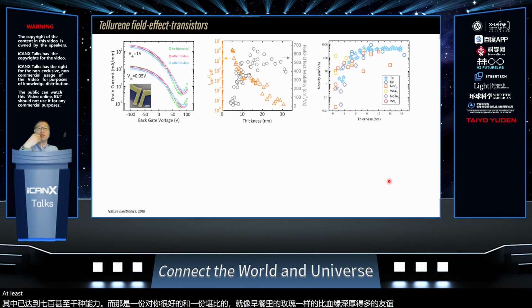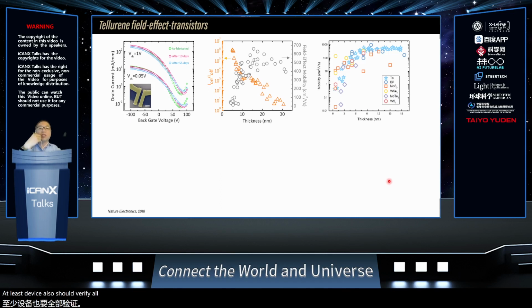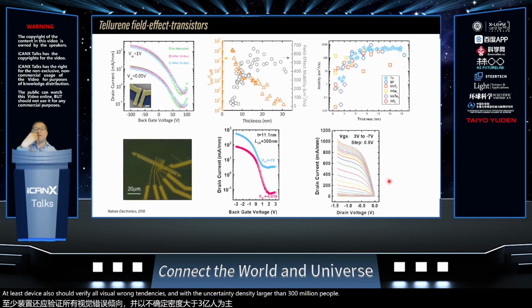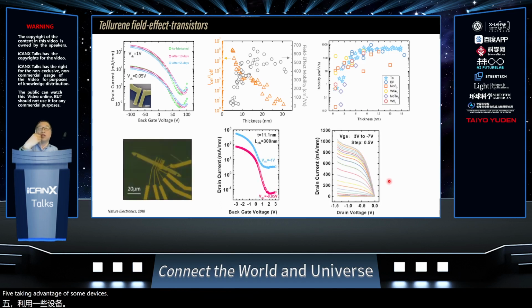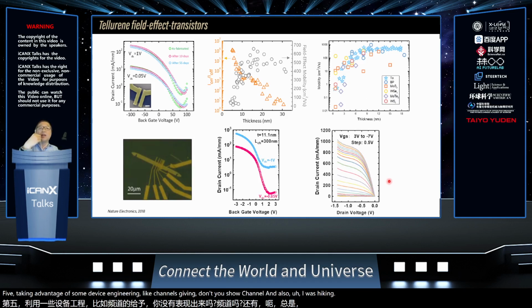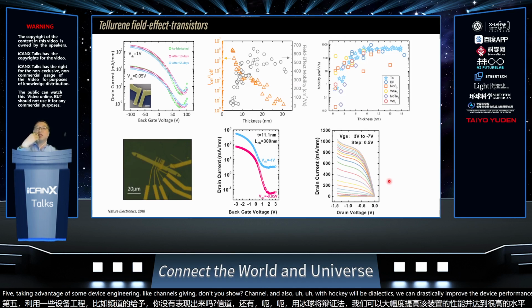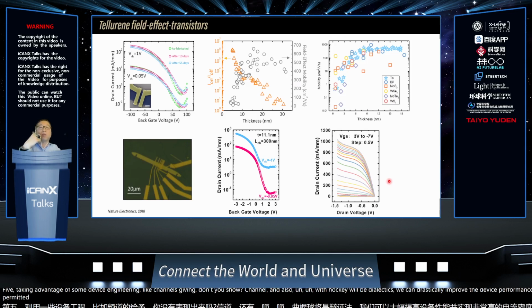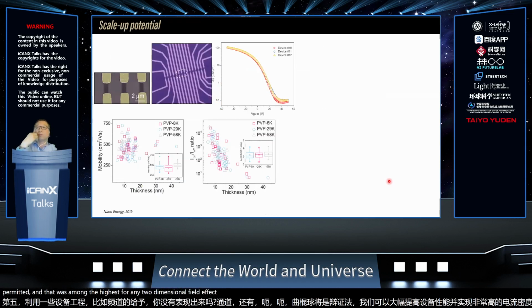This device also shows a very high on-off ratio, around 10 to the 5th, with an on-current density larger than 300 milliampere per millimeter. By taking advantage of some device engineering, like scaling the channel down to a short channel and using high-k ALD dielectrics, we can drastically improve the device performance and achieve a very high current density of up to about 1 ampere per millimeter. That is among the highest for any two-dimensional field effect transistors.